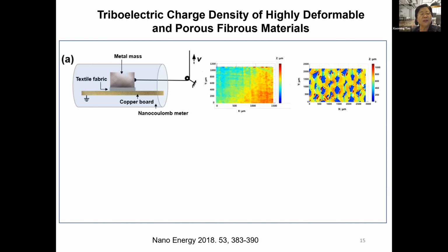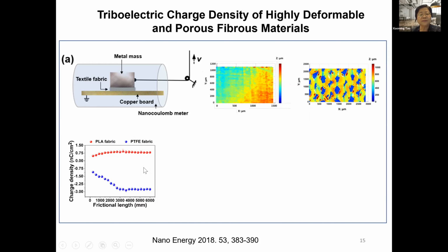And you can see a large pore present in the fabric. When we do this measurement, we're trying to determine the charge density due to triboelectric action. The experiment setup is like the one at the top. We're using sliding mode, and the fabric is placed on conductive plates. And you will find it interesting, charge density is not constant. Initially, the density is low. There are two materials, one positive, the other negative.